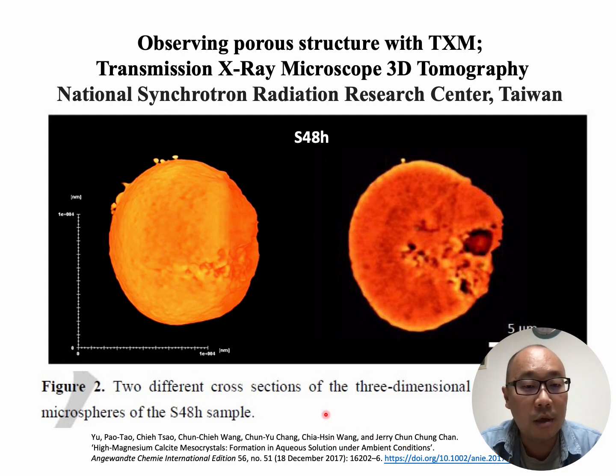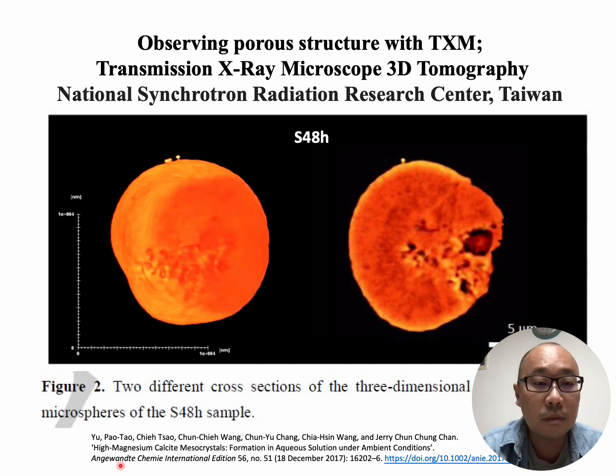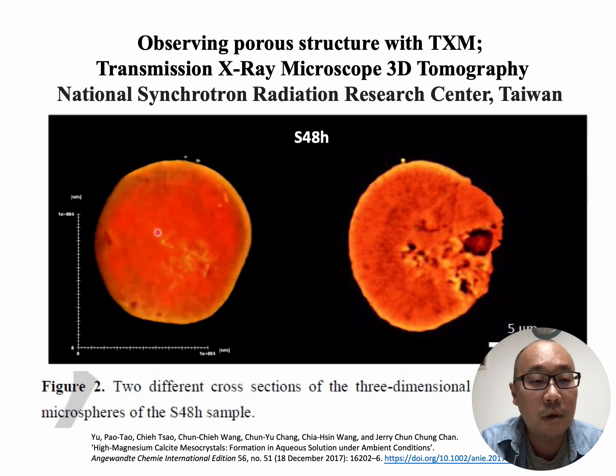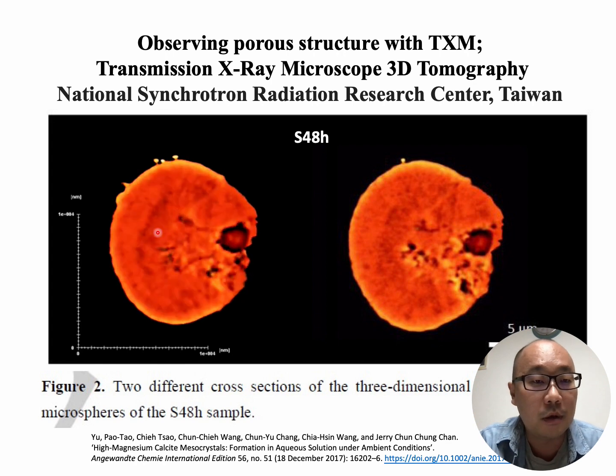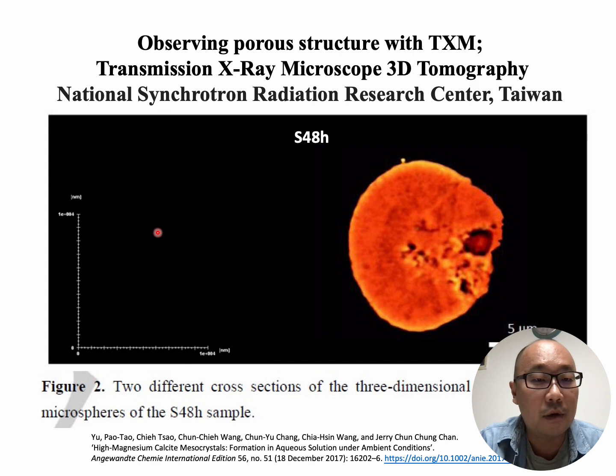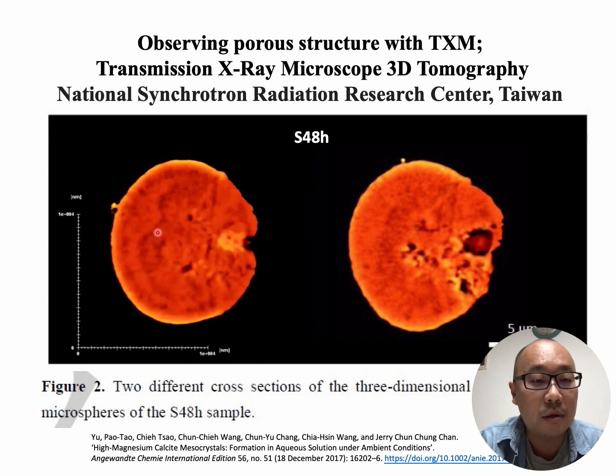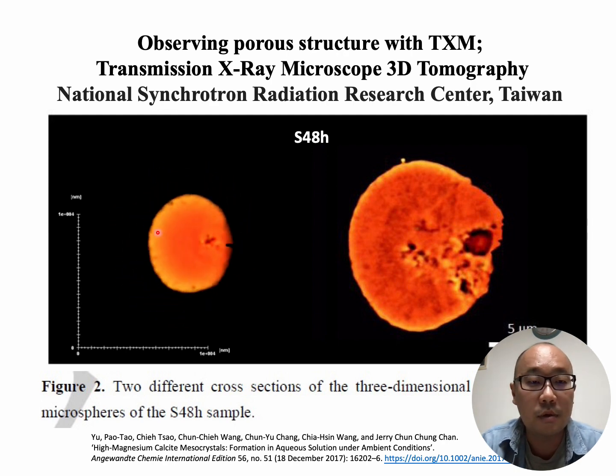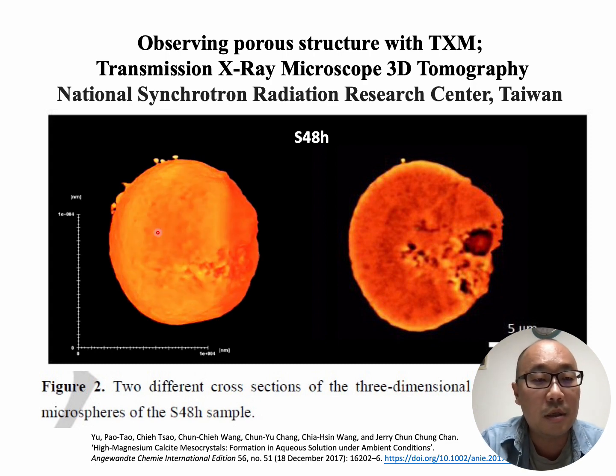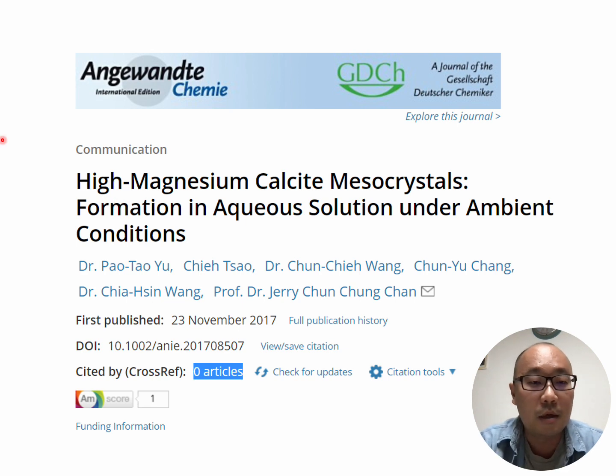That's the first publication in Angewandte. That's in our lab, the first publication in the Angewandte paper. So let's see the imagery cartoon and the video that shows the different slide for each slide of the spherical particle, and they use the algorithm to collect all the data and to show the imagery, 3D imagery. It's very similar to the CT results, but the resolution in the synchrotron radiation is 60 nanometer. Okay, so that's the publication. We use this title for our paper. That's high magnesium calcite mesocrystals, the formation in aqueous solution under ambient conditions.